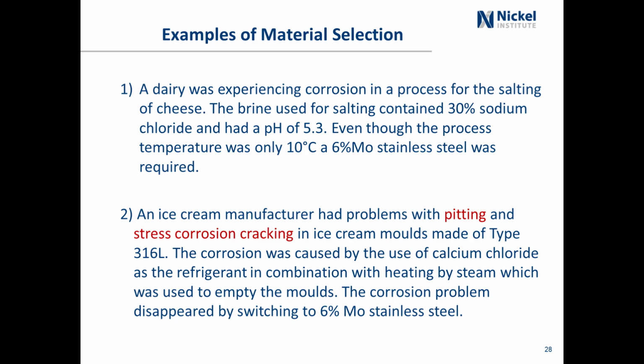An ice cream manufacturer had problems with pitting and stress corrosion cracking in ice cream molds made of type 316. The corrosion was caused by the use of calcium chloride as the refrigerant in combination with heating by steam, which is used to empty the molds. The corrosion problem disappeared by switching to 6% molybdenum stainless steel. But in this case, the corrosion wasn't caused by the ice cream, it was caused by the chloride solution that's used as a refrigerant. So this is a case where it's the process that dictates what stainless steel needs to be used.